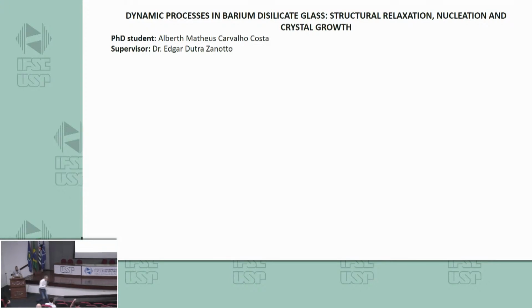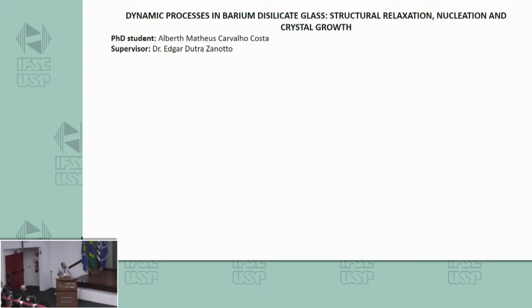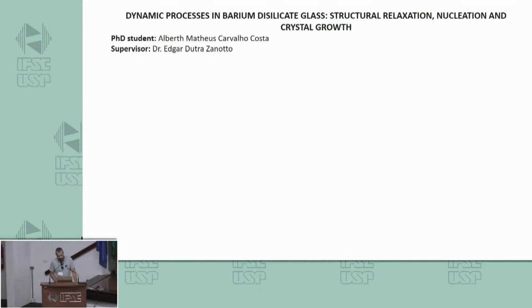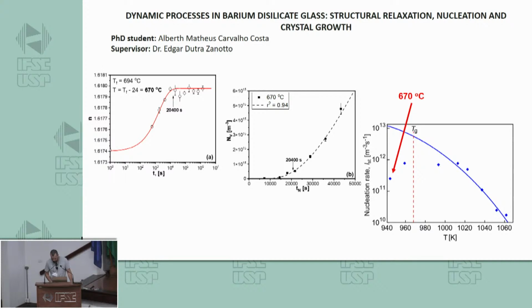My work is entitled Dynamic Processes in Barium Disilicate Glass: Structural Relaxation, Nucleation, and Crystal Growth. My first result about the isothermal heat treatments showed that the crystal nucleation rates below the glass transition temperature need more time to reach the nucleation ultimate steady state, as we can see here in the figure at the right.